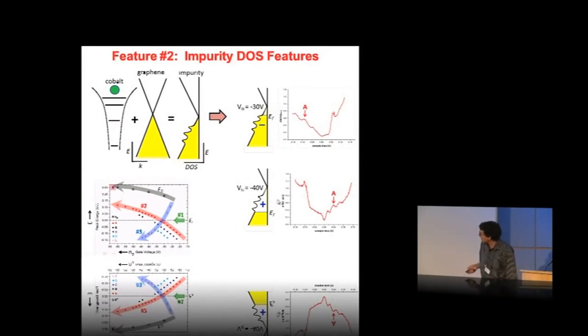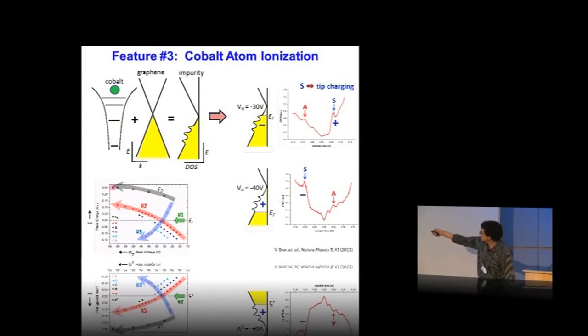Now you might also have noticed these other little states right here that I've marked with the S. Those states are due to tip-induced charging of the defect. And a nice way to think about it is we have an atom sitting on the surface. We gate the sample, and that determines a charge state for the atom. But then we can bring the tip in, and the tip is also a gate. It's a movable gate. It's another gate. And we can bring that tip in, and then we can use the tip to change the charge on the atom.